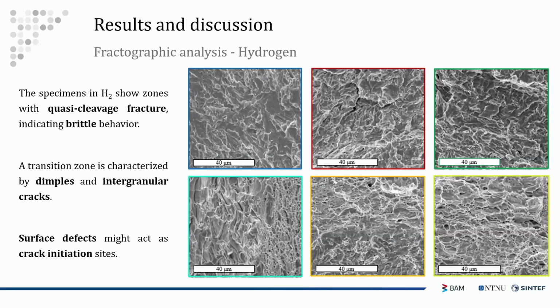Going to the higher magnification, we can clearly see the presence of quasi-cleavage fracture in the outer area of the solid specimen and in the inner part of the hollow specimen, so the closer part to hydrogen. While there is a transition zone that is characterized by the presence of both dimples and intergranular cracks, which shows how hydrogen permeated up to a certain part of the specimen in the radial direction. And we figured out, considering the portion of quasi-cleavage fracture and microvoid coalescence, that surface defects have a strong impact because they can act as crack initiation sites. So the fraction of quasi-cleavage fracture is way higher in the case of the drilled specimen.